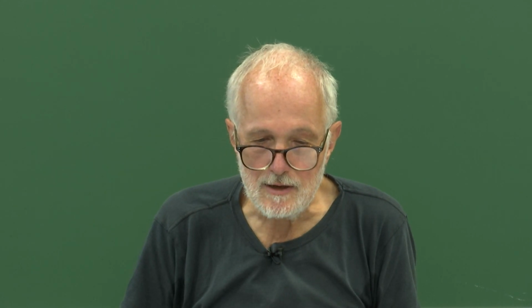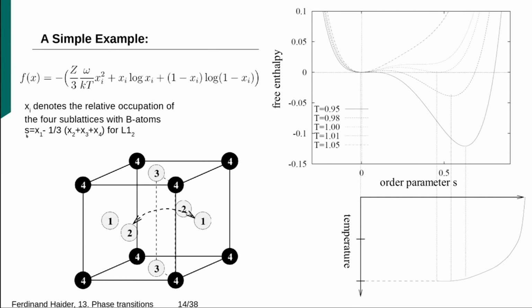So we can define an order parameter like this here. You take the occupation of one of the sublattices minus 1/3 of the sum of the other 3 sublattices. I should have called this one 1 here. So if all sublattices are equally occupied with 1/4 of the B-atoms, you get 0 here. If all are sitting on one sublattice, say on sublattice 1, then you get an order parameter of 1.